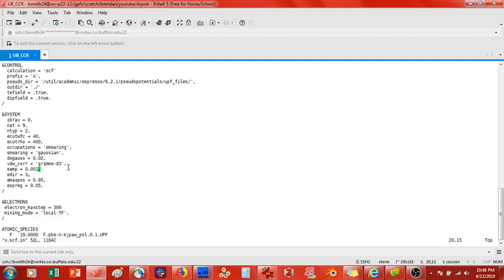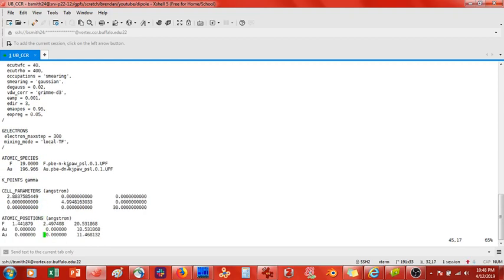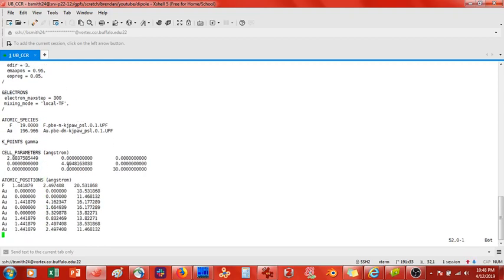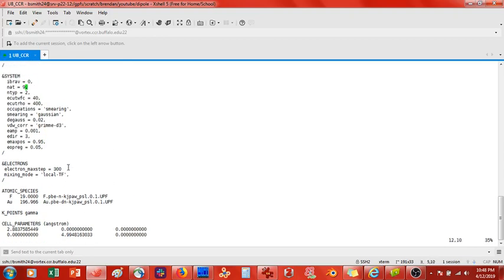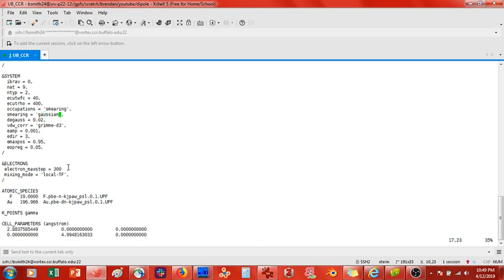So this is the only thing we actually have to change. The rest of the input file is exactly how it was last time. There's a couple things I want to mention, as I do usually in these videos. The structure of gold I am using here has not been converged with respect to ECUT. It has not been converged with respect to K-points, and it has not been converged with respect to Gaussian smearing or any type of smearing. I don't think you would want to use Gaussian smearing for a metal. You might want to use the other one. It's MV smearing. I can't think of it off the top of my head. I was reading an article on that the other day, but there's a better smearing for metals.